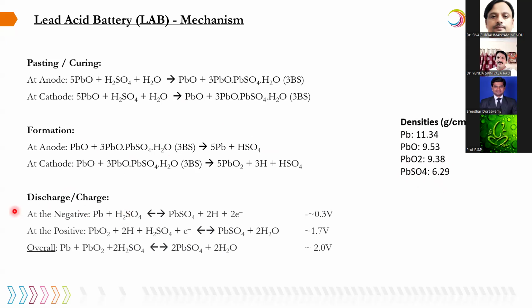If you see here, at the discharge condition the negative metallic lead converts into lead sulfate, leaving out 0.3 volts. At the positive, lead dioxide reacts with the hydrogen and sulfuric acid and two electrons from the negative, thus forming lead sulfate and leaving water, and it delivers around 1.7 volts. So the combination of both positive and negative, 1.7 and 0.3, gives out 2 volts. So this is how a lead acid cell delivers a 2-volt electromotive force.